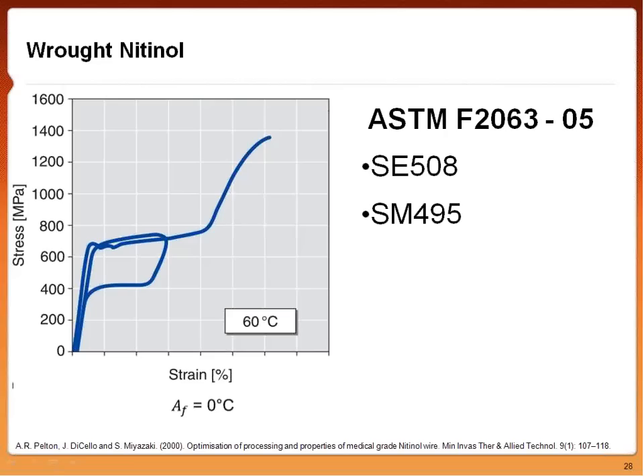So again, we go back to that typical stress strain curve for a sample that has an austenite finish of 0 degrees Celsius and a test temperature of 60 degrees. Now, when we look at the type of material we want to choose, nitinol comes in basically two flavors according to the ASTM standard: Superelastic 508 or SM495. Superelastic 508 means it has 50.8 atomic % nickel, and SM495 means it's shape memory with 49.5% nickel content.